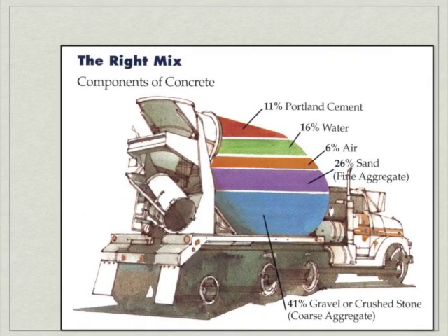Here is a diagram of a typical concrete mixture. As you can see, 67% of this mixture is aggregate. Ready-mix producers will always choose their aggregate first and foremost based on availability. They'll try to find the hardest, least deleterious, least reactive material. As an example, in New England, a great deal of granite is used, while out in Indiana, it is mostly sedimentary rock. And in the Palisades of New Jersey, it will be all basalt.